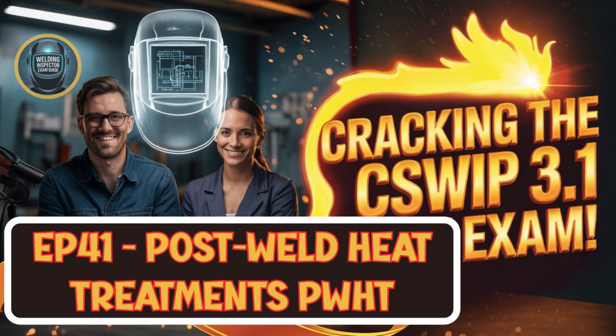Parameter 2. That's the soak temperature range. This is the actual temperature you hold the part at for the stress relief or tempering to happen effectively. And it's not one size fits all. It depends very specifically on the type of steel. Your standard carbon and carbon manganese steels might need around 600 C, that's about 1100 F. But for the tougher, low alloy steels like chromoly steels used in high temp, high pressure stuff like power plants or refineries, they need higher temperatures, often up around 700 to 760 C. That's like 1300 to 1400 F.